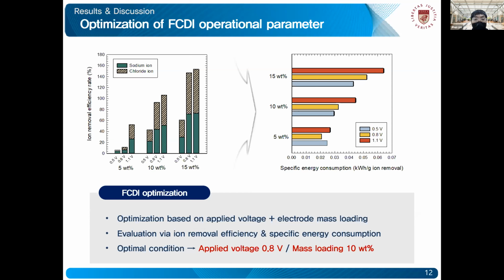Now, moving on to the subsequent FCDI part. The FCDI process was initially investigated for the optimal operational conditions. The optimization was based on applied voltage and electrode mass loading, and the evaluation of the optimization parameters was based on ion removal efficiency and specific energy consumption. As we all know, higher applied voltage allows stronger attraction of the target ions, leading to increased removal. Higher mass loading also leads to increased removal in that the electrode particles act as a bridge for charge transportation. Thus, higher electrode mass loading also allows the formation of strongly defined charge percolation pathways, thereby improving the overall charge efficiency of the system.